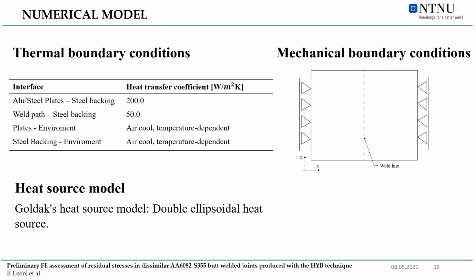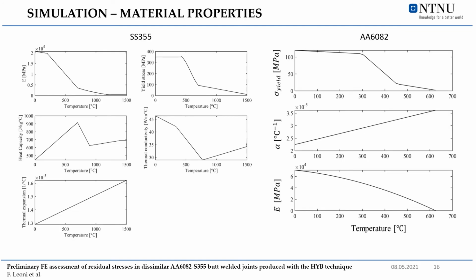These simulations were set considering these thermal boundary conditions. In the table you can see that different heat transfer coefficients were set between the plate and the steel backing, and between the weld path and the steel backing. Moreover, the air-cooling effect was also considered. The shown material properties, as a function of temperature, were set for the two materials. Elastic-plastic behavior was considered.